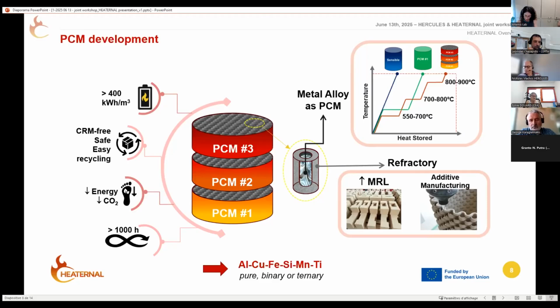So precisely, in the HEATERNAL project, we had the objectives to develop some composite materials of metallic PCM for thermal storage between 600 and 900 degrees with some requirements. Its storage capacity over 400 kilowatt per cubic meter, proven lifetime over 1,000 hours, and the materials with low energy and carbon footprint, free from CRM, not toxic and safe, and easy recycling. So taking into account all these requirements, the PCM we have developed during the project are pure aluminium or binary and ternary alloys from the aluminium, copper, iron, silicon, manganese, and titanium system.